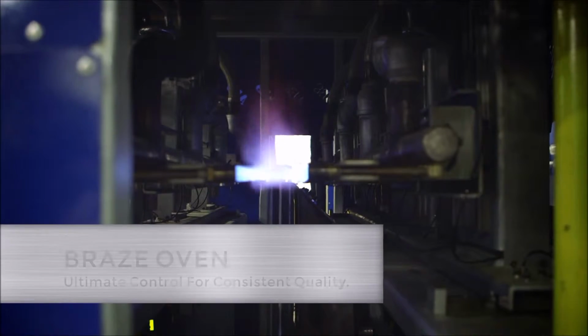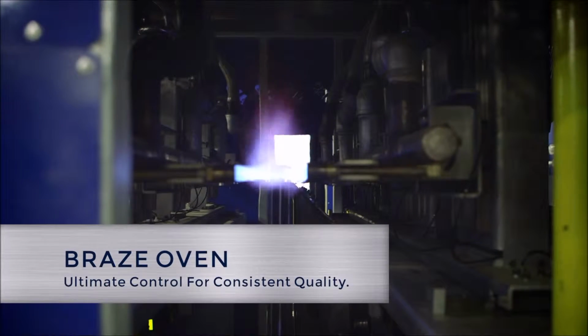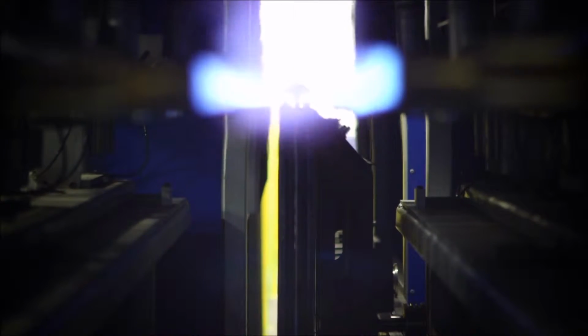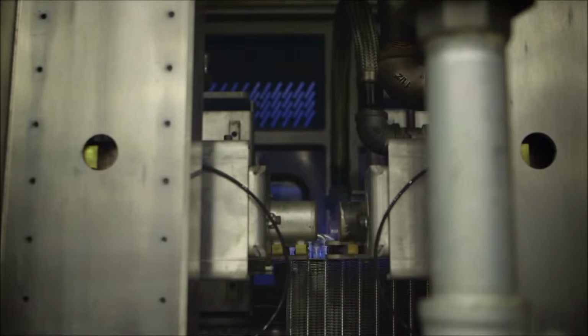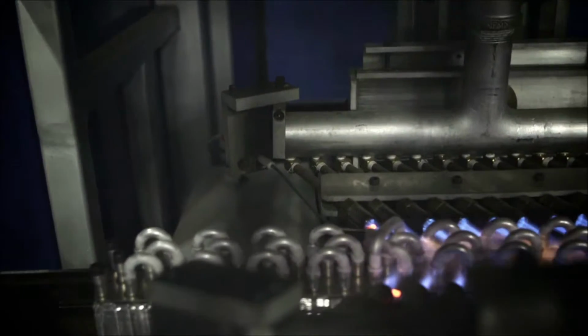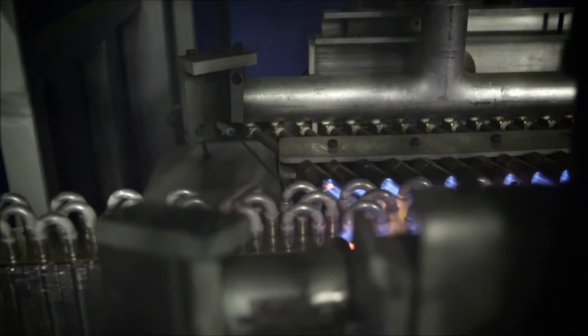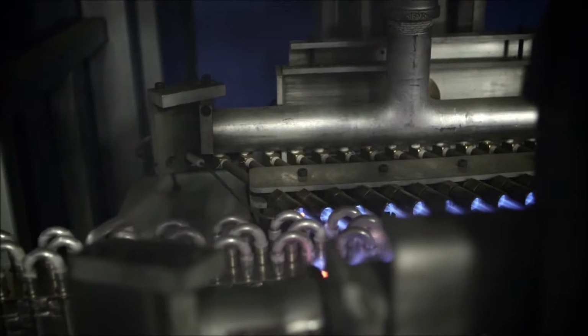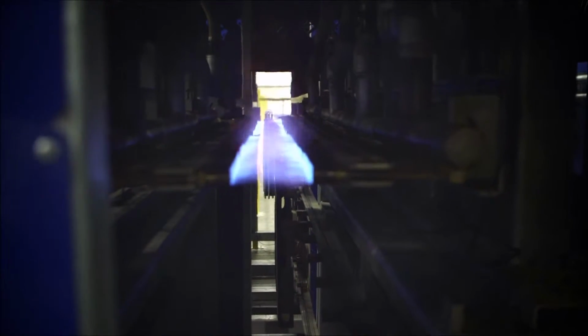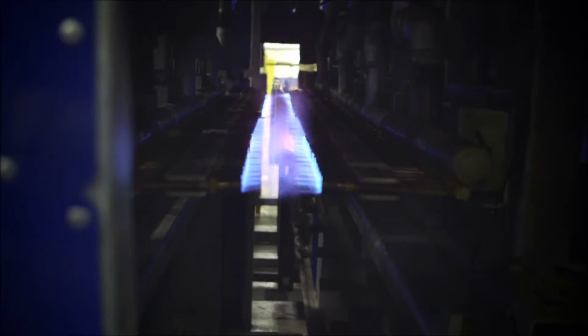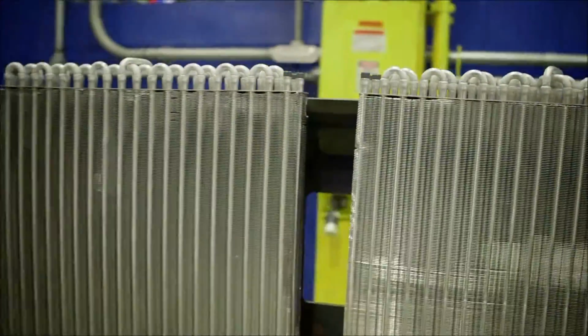Brazing aluminum is uniquely different from other alloys in that the temperature window between the alloy and the base metal is less than 100 degrees, requiring close control of brazing temperature for an effective joint. Our special braze oven has temperature data feedback in 4 unique zones to accurately control penetration of the alloy in the braze joint, creating a consistent joint for years of leak-free operation in the field.